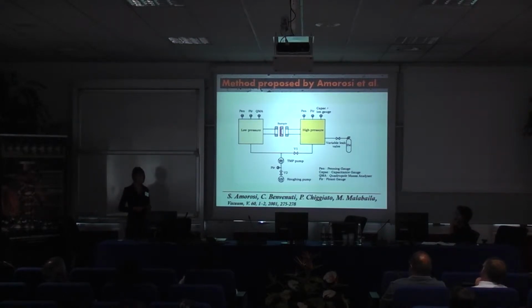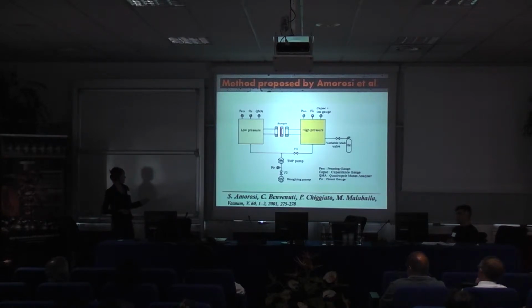For this, a niobium film was deposited on disc copper substrates, and afterwards copper was etched in the central part of the substrate. This copper washer with a niobium coating was placed between two vacuum chambers. In one, helium gas was inserted, and in the other one, the throughput of helium was measured. This allowed identifying the surface area of the pores in the film.